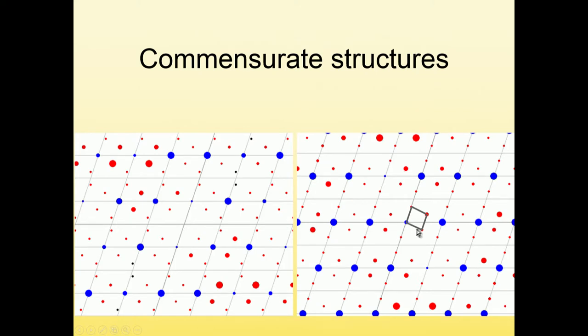And you can find a smaller reciprocal cell that describes all the spots on one periodic reciprocal lattice. But these two structures are so closely related that it's almost obvious that they would benefit from the same description. And you can indeed do this: refine the structure, find the modulation functions, and then just change the value of the Q vector to the commensurate value, and you get a good fit to the diffraction pattern of the commensurately modulated phase.